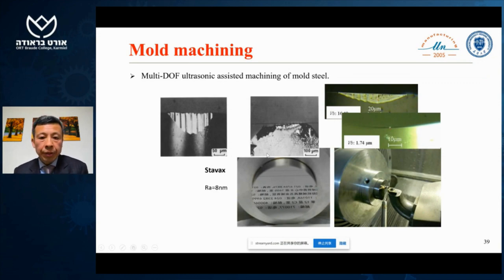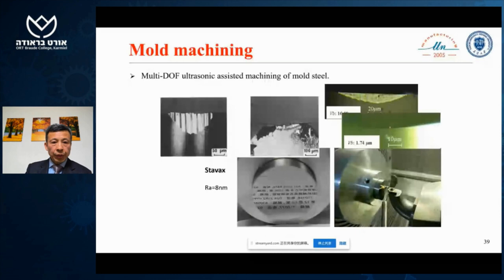Another very important material is carbon steel. There's a problem using nanometric cutting process to generate complex surface on carbon steel, particularly for mold steel. So we developed so-called multi-degree of freedom ultrasonic assisted machining. Ultrasonic assisted machining is not a new process. So many researchers have done a lot of work in this area. However, there are very few successful applications in industry. So we developed this kind of technology and further developed this process.